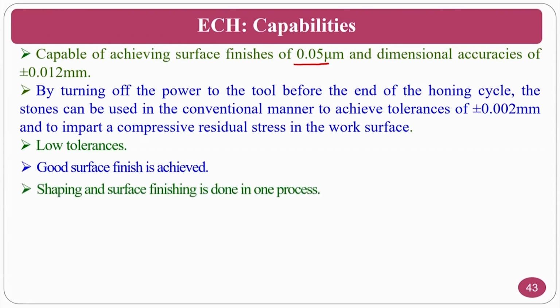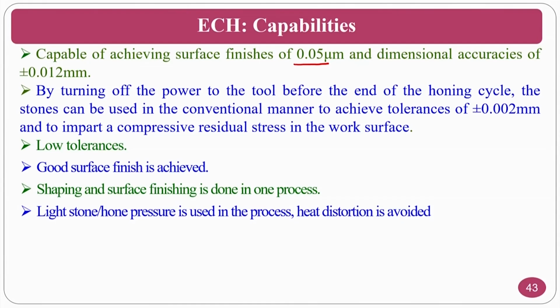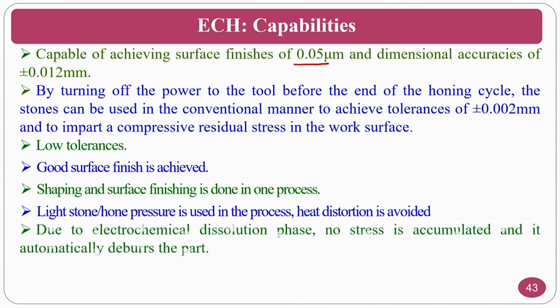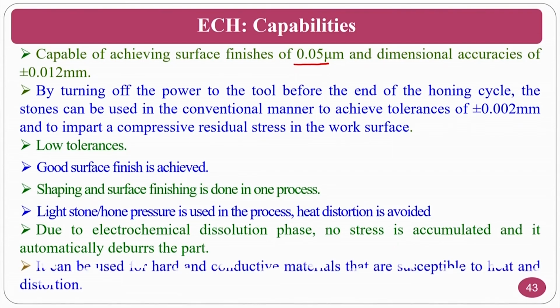Good surface finish you can achieve, and the shaping and surface finishing is done in this particular process. So, light stone or hone pressure is used so that heat distortion will be avoided. At the same time, due to electrochemical dissolution phases, no stresses are accumulated and the deburring action is not required, because as I said, everything will be taken care of by this particular process by the electrochemical dissolution. It can be used for hard and electrically conductive materials.